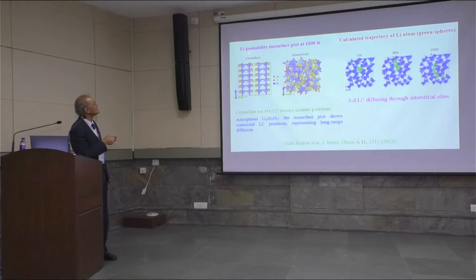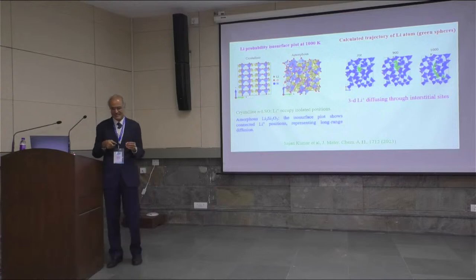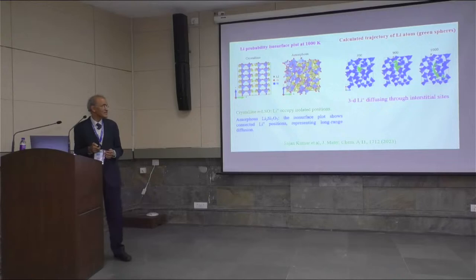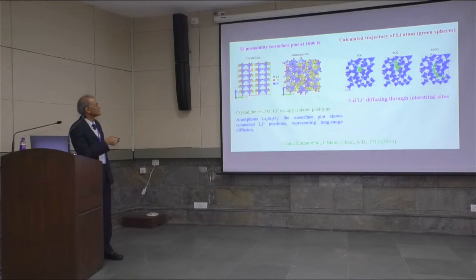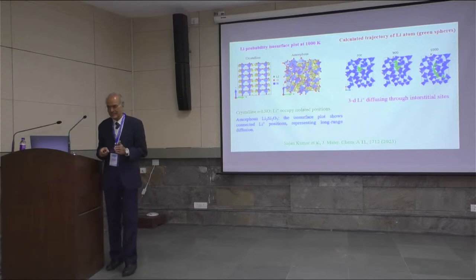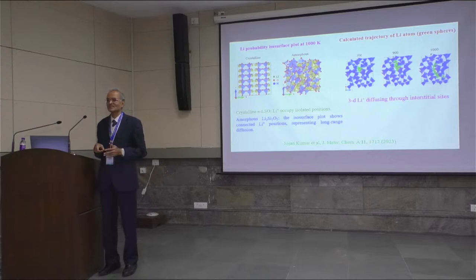In the molecular dynamics simulation, as you know, you calculate the trajectories of atoms as a function of time, typically on the order of picoseconds. And then if you look at this, for example, in this crystalline material, the atoms are located at definite sites. Whereas if there is diffusion taking place, then this will not be so. So these are just the probability isosurfaces. Initially, the temperature has to be very high, because in a small simulation, in the real world, you can go up to seconds or minutes and so on.